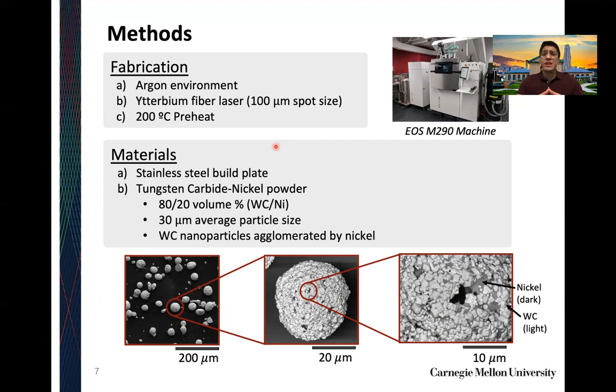Now the materials themselves, all 3 builds were done with a stainless steel build plate. The tungsten carbide nickel powder was a novel, very unique composite powder, which, as I said previously, has an 80-20 volume percentage, 80% tungsten carbide, 20% nickel. And the average particle size was 30 microns, which is indicative of good flowability because we need to have a large enough powder particle in order for the powder to flow well and deposit nice flat even layers.